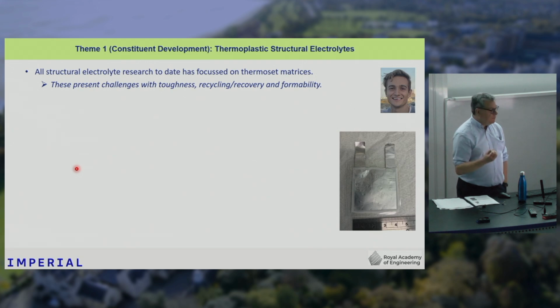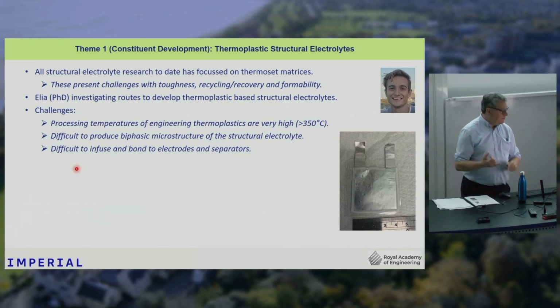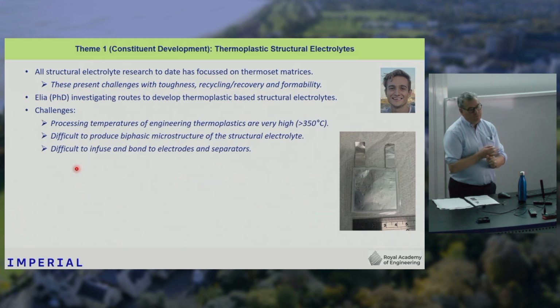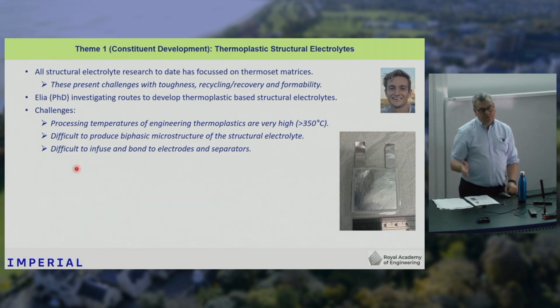So we have effort at the moment to try and look at getting thermoplastic structural electrolytes rather than thermoset structural electrolytes. So the challenges here are that the processing temperatures for conventional high performance thermoplastics are enormous, 350 degrees C. So those high temperatures are going to be problematic in terms of producing a material which has functions, because a lot of those functions are going to be damaged by excursions into those temperatures. Producing that biphasic structure in a material that you're processing at those temperatures is also going to be very challenging.